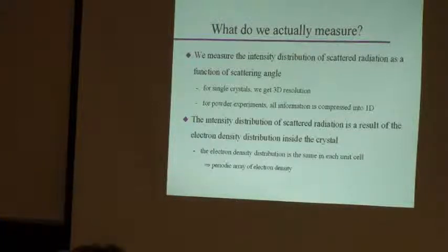Okay? If we have a single crystal, we can do so in 3 dimensions. And just for simplicity, we don't just move the detector, we also usually move the crystal, because that way we don't have to move anything as far. For a powder experiment, usually you get your information in 1 dimension. Okay? Most X-ray powder instruments have a detector that moves on 1 arm, so you get 1-dimensional data.